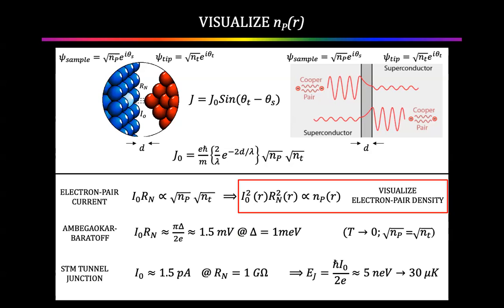All right, this can never work for the following reason. If you take a conventional, this is the Ambegaokar-Baratoff equation. If you take a conventional energy gap here, let's say a millivolt, okay? And if you take a typical STM junction resistance, let's say a gigohm, then you will find out that the Josephson energy is a few nanoelectron volts. Or the Josephson characteristic temperature of the junction is a few 10 microkelvin. You can't stabilize the phase difference of a single atom Josephson junction with the junction resistance of a gigohm the way you do with an STM. No one has ever succeeded to do that.